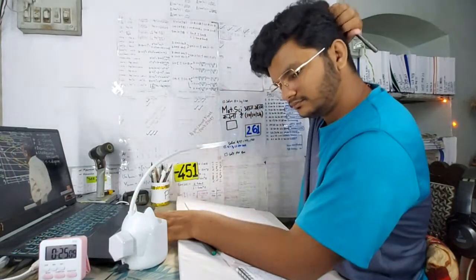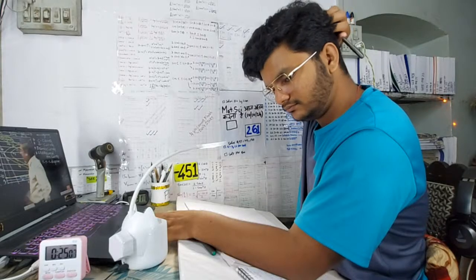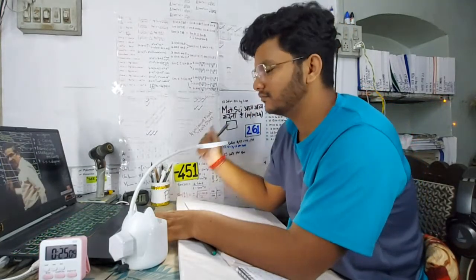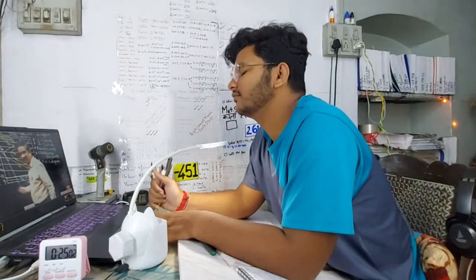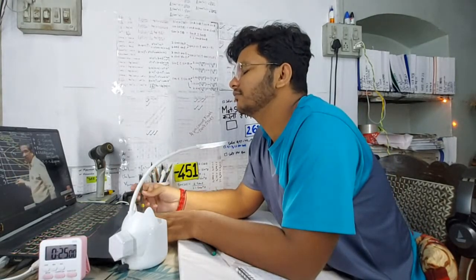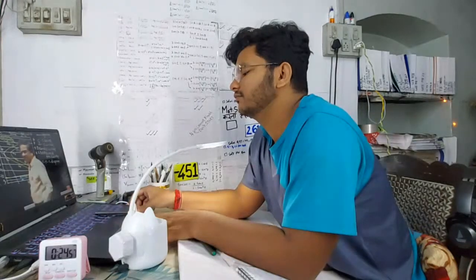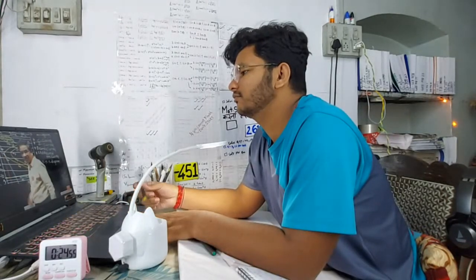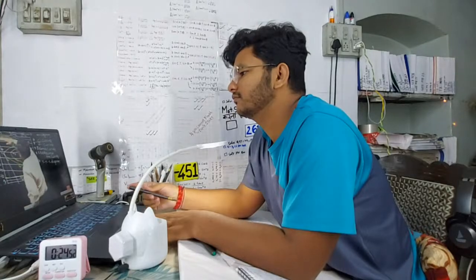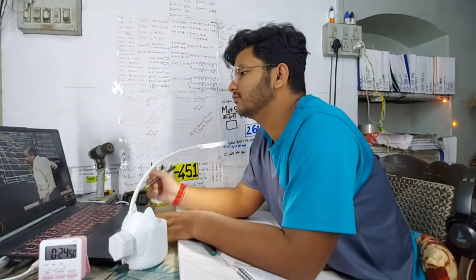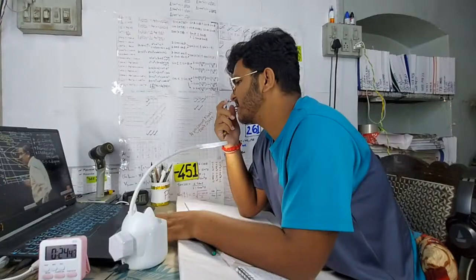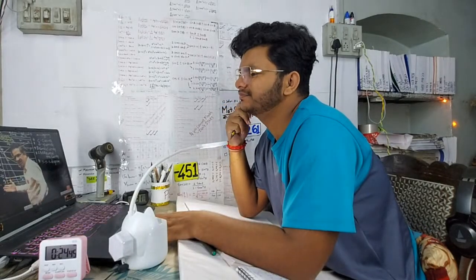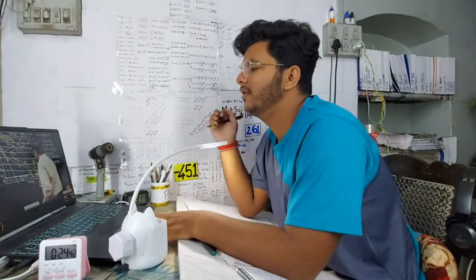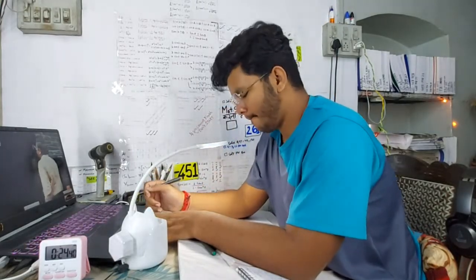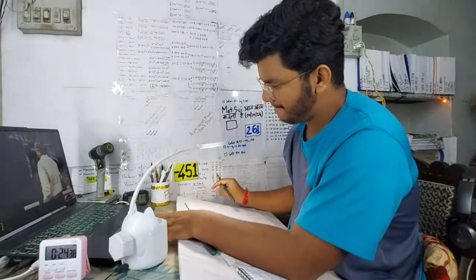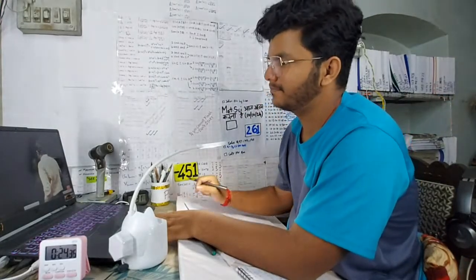Right? So this is the question in your workbook. As you go from curve number 1 to the red color curve, what happens to the transformation time? Transformation time decreases. Out of all these curves, which curve will take lowest time for transformation? Red color curve will take lowest time for transformation. Correct? Because you see here, as you are going from first curve to the red color curve, what is happening on the x-axis? You are going from right side to left side, time is decreasing. Transformation time is decreasing. Right. Once you have identified this, let us quickly develop further understanding about other types of hardening techniques. We'll try to show them here.